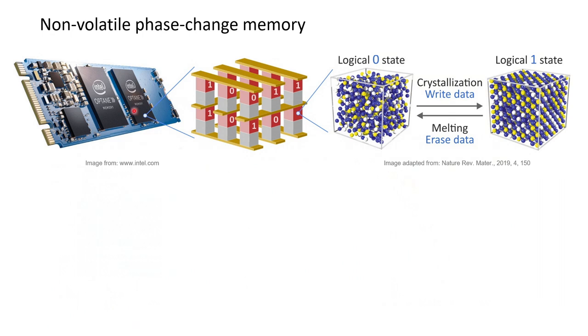The application is called non-volatile phase change memory. This is a new storage class memory that is already better than silicon transistors. It's on the market, and basically the working principle is very simple. This is a structure conversion of the same material from the amorphous to the crystalline through the crystallization and melting phase transitions, which brings us to the logical 0 state, the highly resistant state, and the logical 1 state, the low resistance state.